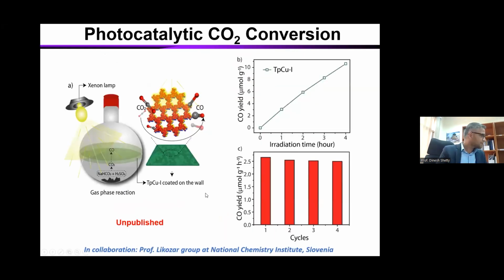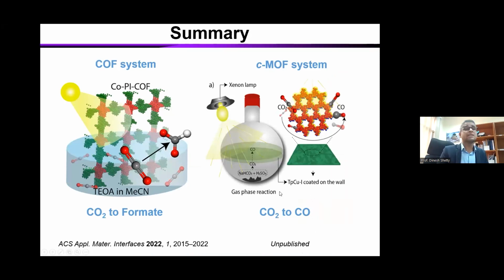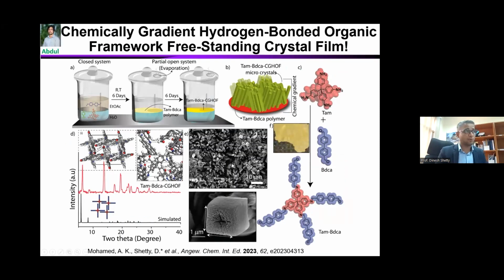And what did we do with this? We used this conjugated system to do CO2 conversion, in this case CO2 to carbon monoxide. It's another very important industrially valued gas, right? So in this case, we ended up getting a decent conversion of CO2, 100% selectively, because we checked whether it is giving any other gas products. It's not, and also we could reproduce that result for at least 4 cycles. Okay, so this is the story so far.